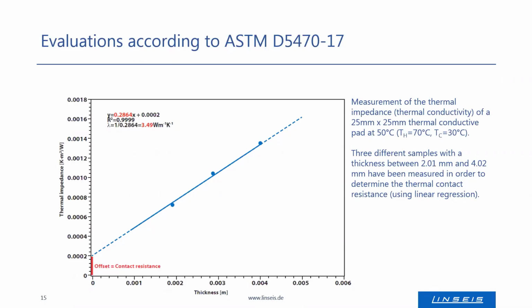From the linear fit, one can then determine on the one hand the thermal conductivity. The thermal conductivity corresponds to the inverse of the slope of this linear fit here. And with the y-axis interception, or the offset, one can determine the contact resistance.